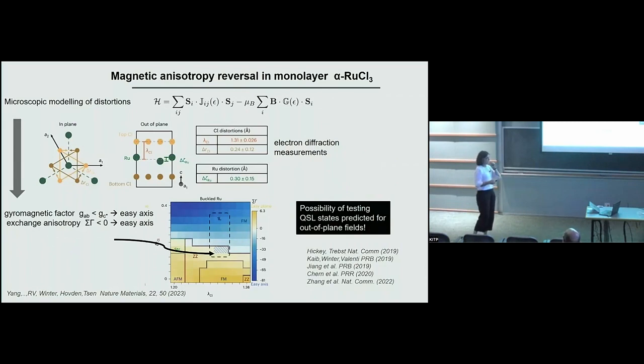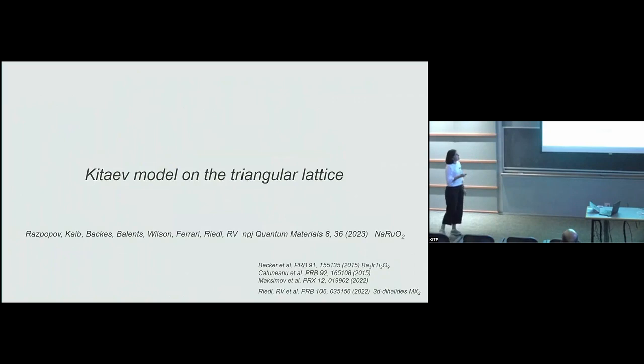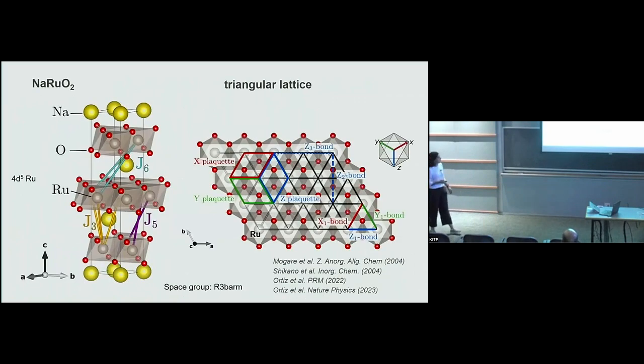I have 1 minute. Okay, so I go now to the triangular lattice for 1 minute, to test all these models that have been proposed for spin liquids when you apply a magnetic field perpendicular to the layer and not parallel. We had last week a very nice talk by Stephen Wilson about sodium ruthenate, a triangular lattice system, which, since you have ruthenium again, you would expect bond-dependent exchange interactions.